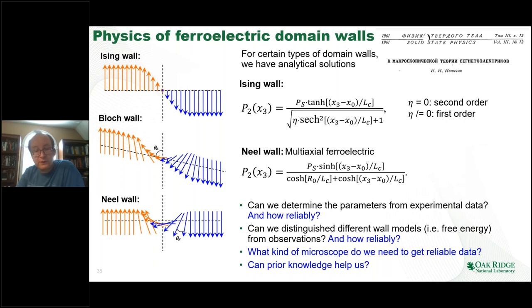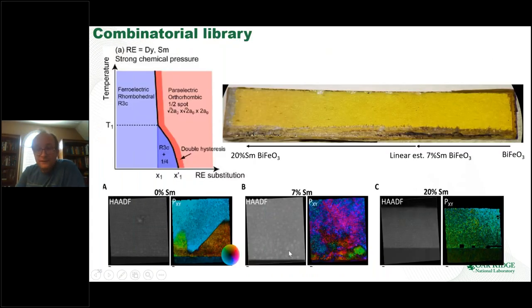So how do we answer this type of questions? And an even more interesting question is, imagine that we have two people looking at these ferroelectric domain walls. One person knows the physics of ferroelectric materials, and the other person does not. So can the prior knowledge help us to answer the questions about the physics of these walls from observations? The example of the system that we explored here is this combinatorial library of bismuth ferrite. It's a very convenient sample where, on the one hand, we have a doped bismuth ferrite, which is paraelectric and orthorhombic. On the other hand, we have a pure material. Pure material has a nice ferroelectric domain wall, so we can use it for our studies.